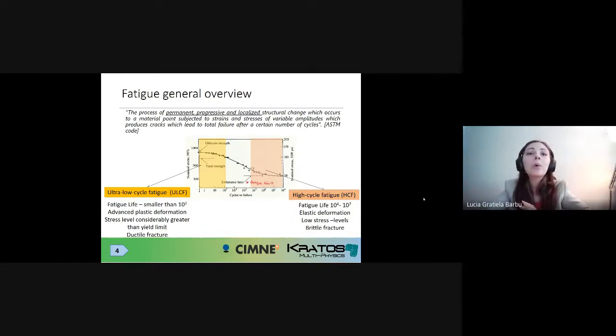Here we have quite low fatigue lives, in the order of dozens of cycles, maybe hundreds of cycles. We are dealing with a behavior which is completely different from high cycle fatigue. We have advanced plastic deformation, and the stress level is considerably greater than the yield limit. And the fracture in this case is very ductile.